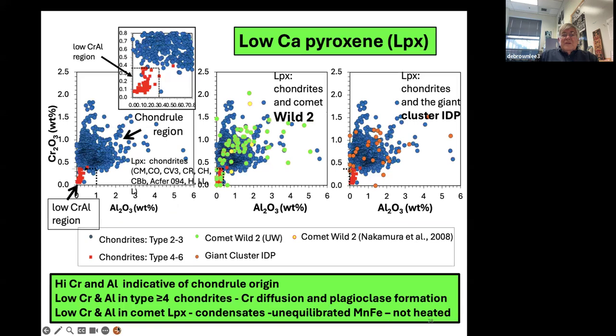We also have an interesting clue from low calcium pyroxene, and Dave Josvik has done a lot of interesting work on that. These are plots of Wild 2 and Giant Cluster IDP, interplanetary dust particle, and meteorites on the left. The chromium aluminum in low calcium pyroxene from chondrules plots in that blue region on the far left, and generally that's a good agreement with Wild 2 and the cometary IDP. So we believe that the high chromium and high aluminum is indicative of a chondrule origin.